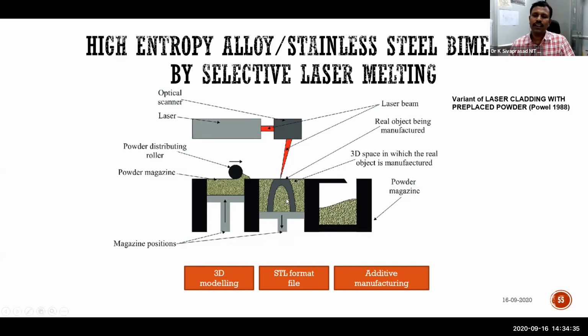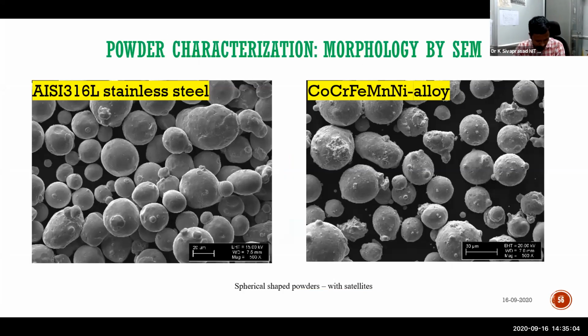Like that, based on laser movement, which is controlled by an AutoCAD diagram, the coordinates of the laser movement can be controlled very efficiently to even less than micron precision. So you will get your final product very accurately. And if you are able to optimize your melting rate, melt overlapping and other things, you can significantly reduce your porosity also. Those who are working in additive manufacturing are very well versed in that. You are supposed to use atomized powders only, so that the powder flow and other things will be very comfortable.